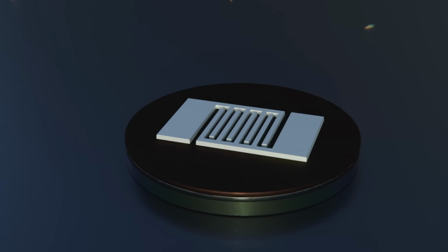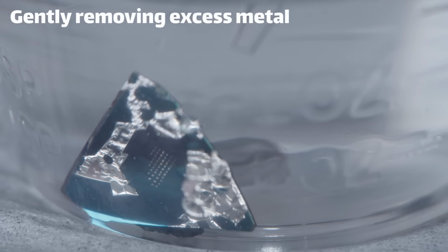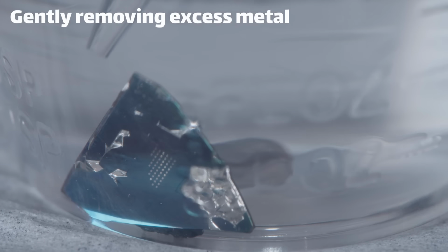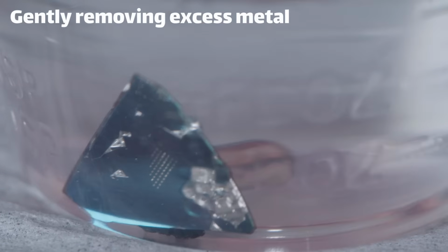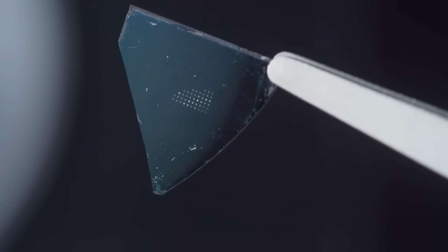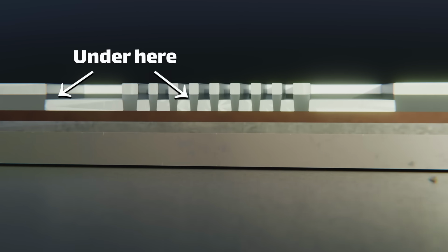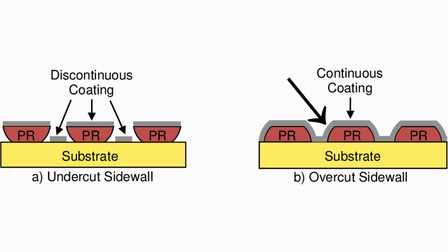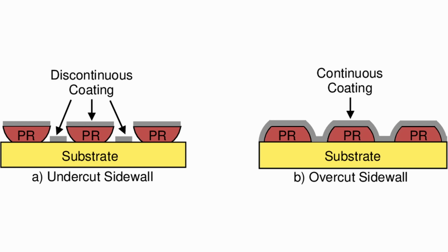This is called a liftoff process because we're physically lifting the metal off instead of using something like a chemical etchant to dissolve it. For liftoff to work well, you need a solvent to get underneath the metal and dissolve that in-between resist layer. However, this only works if the sidewalls of the resist remain uncoated with metal. If we have sidewalls that are sloped outwards, for example, the deposition process will coat them in metal just like the top surface, and there's no way for the solvent to get in and dissolve the underlying resist. So we need vertical, or even ideally inward sloped sidewalls.